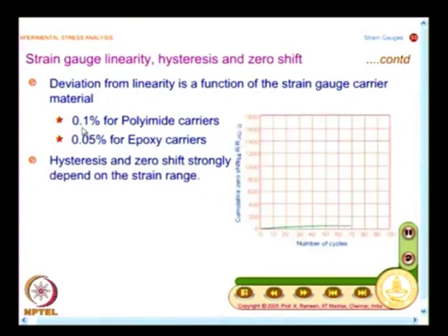What you find is polyimide carriers, the deviation is about 0.1%. On the other hand, if I go for epoxy carriers, it is just half of it, it is about 0.05%. But you know very well polyimide is easy to handle, it is a plastic, even a beginner can handle this polyimide carrier. We have already looked at epoxy is brittle, that is recommended for transducer applications. So, what you find is when I want to improve linearity, hysteresis, zero shift, I need to go for sophistication. It comes with a price, it does not come freely.